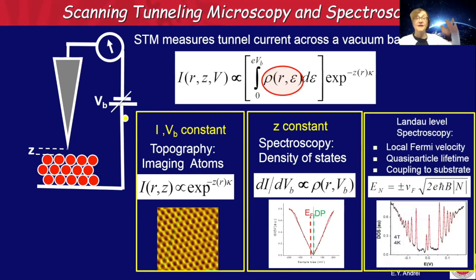Another thing that we can do is apply a magnetic field, and there the Landau levels pop up beautifully. Once you have Landau levels, remember the energy of the Landau level is proportional to the Fermi velocity, the velocity of the electrons in the Dirac cones. By fitting this curve as a function of magnetic field or filling, or level index, you can extract the Fermi velocities. There are other things that you can extract, like quasi-particle lifetime or coupling to the substrate, which I will not discuss. But the Fermi velocity we will use later in this talk.